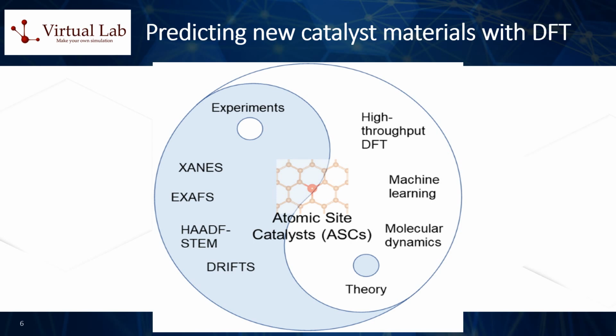For the case of the hydrogen evolution reaction considered here, it turns out that the performance level of the catalyst correlates strongly with the Gibbs free energy of hydrogen adsorption on the catalyst surface, which should be minimized and made as close as possible to zero value for obtaining a maximum catalytic activity and conversion efficiency. For example, for the case of platinum, this free energy parameter corresponds to a very small value of 0.1 electron volts. It turns out that this Gibbs free energy of hydrogen adsorption can be evaluated with DFT by calculating simply the change in total energy across the unfolding of this process of adsorption.